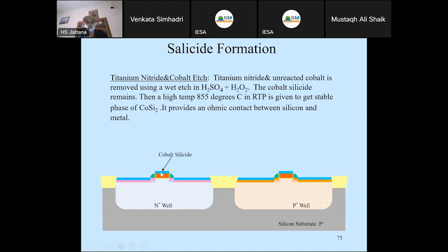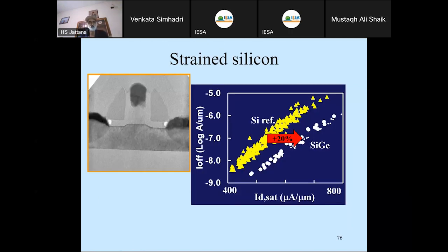So there is a step to deposit the cobalt layer, then to do the patterning, to etch the not required cobalt layer, and then finally after that you have to do the other things. At 45 nanometer, in the channel you have to use a strained silicon, because by reducing the channel length we do not get the advantage, because your mobility suffers.